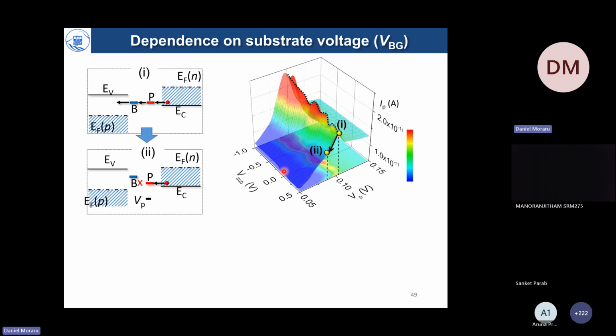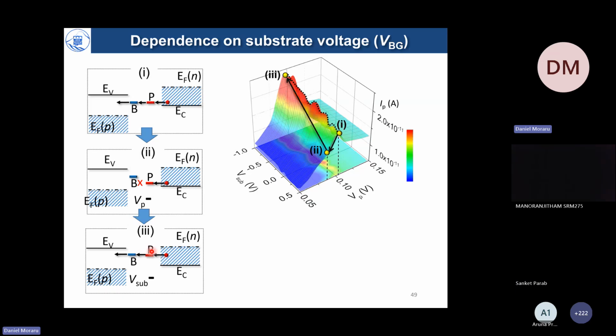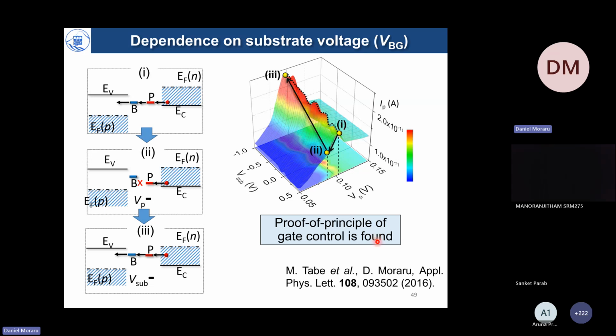If we apply different VP, then we move them off resonance, but we can recover the resonance by applying substrate voltage, which is differently coupled to each of the dopant states. So with this, we have a proof of principle of the fact that gate control is observed, and this was submitted to and published in Applied Physics Letters together with Professor Michiharu Tabe.